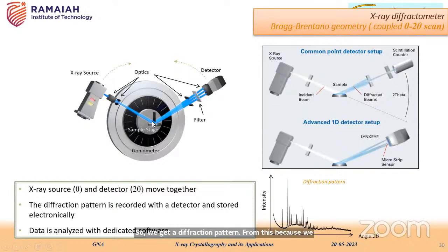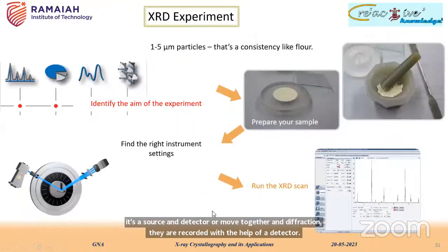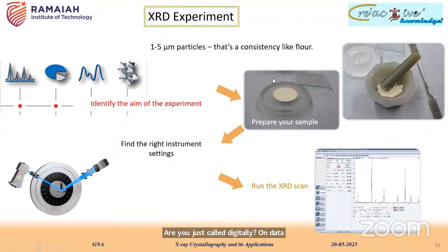So we get a diffraction pattern from this, because here the powder has hundreds of small tiny crystals. When the X-ray falls on these tiny crystals, they diffract collectively, and whenever the Bragg condition is satisfied, the diffracted beams will be detected by the detector, which records the information in the form of intensity versus 2 theta. The X-ray source and detector are moved together, the diffraction pattern is recorded with the help of the detector, stored digitally, and the data is analyzed. This is how the experiment is carried out.